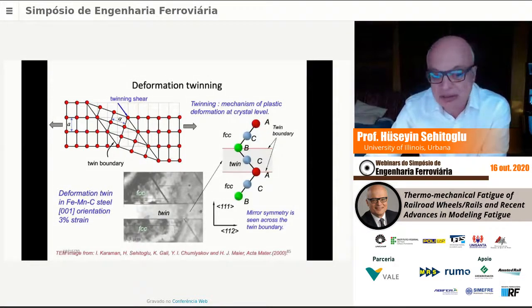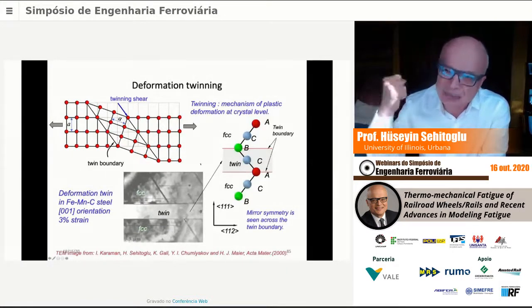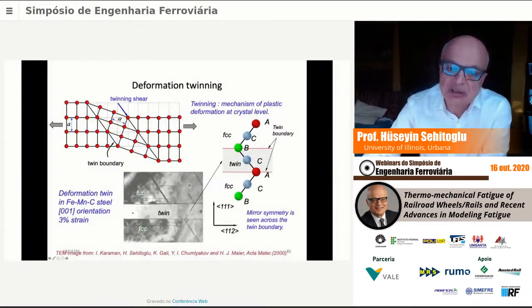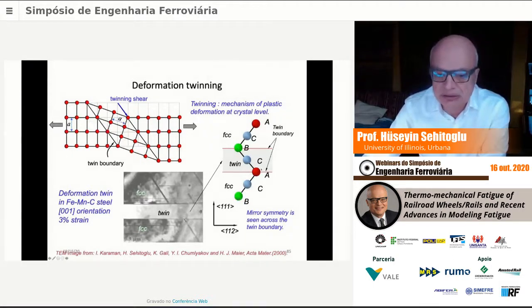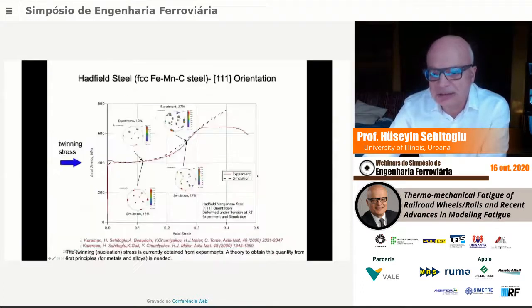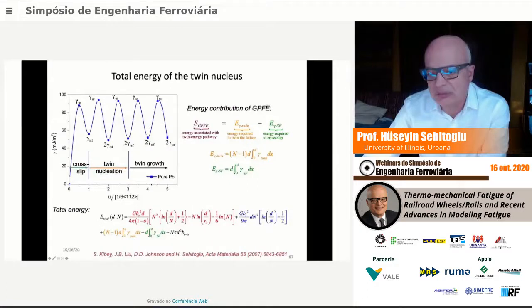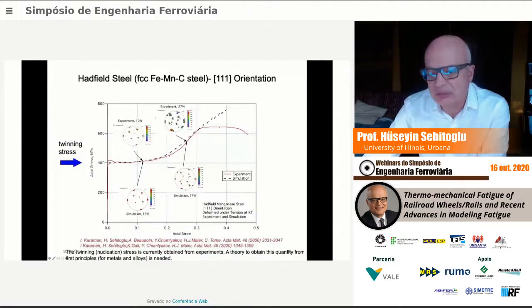They are iron, manganese, carbon materials. They can take up a lot of beating, a lot of plastic flow. Okay? They are far more ductile and tougher than the steels. They do go under twinning deformation, and twinning is like that's the twin, that's the matrix. You could get secondary twin, but this is primary twin here, shown here. A mirror symmetry across the boundary. And that's the twin plane. The stacking is such, normally it's ABC, ABC. But across the twin, you get a mirror symmetry here. The C atom is here, C atom is here, that's the A.